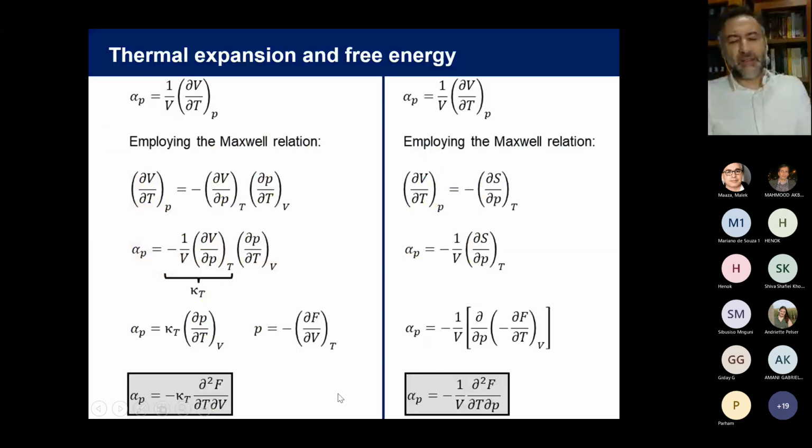And then actually you could ask, wow, but these are very old-fashioned kinds of experiments. Yes, indeed. It's basic physics we are talking about. Essentially, what I want to emphasize here with this slide is the following. When we measure the variation of the volume or the length of a sample as a function of temperature, essentially we are measuring the variation of the free energy F with respect to volume and temperature. Because the thermal expansivity is proportional to the second temperature and volume derivative of the free energy, as indicated here in this rectangle.